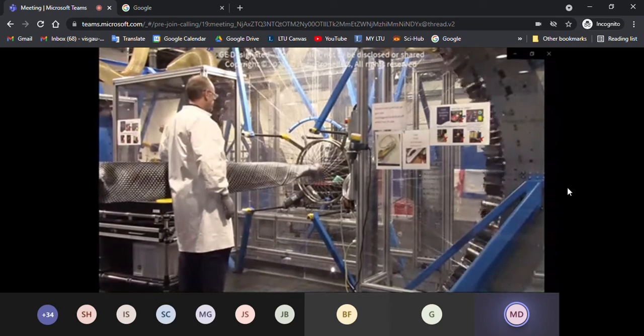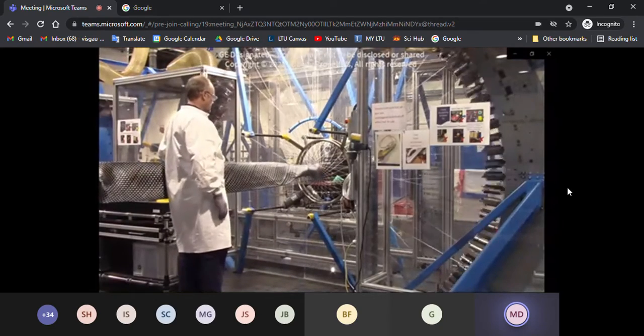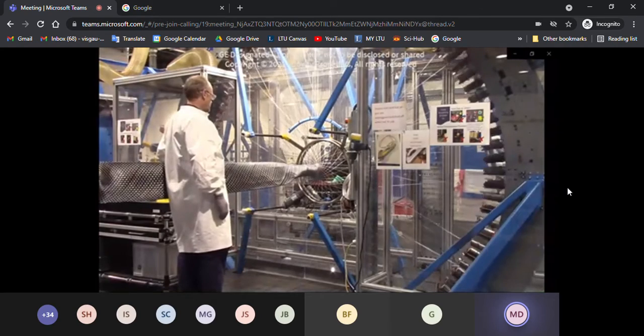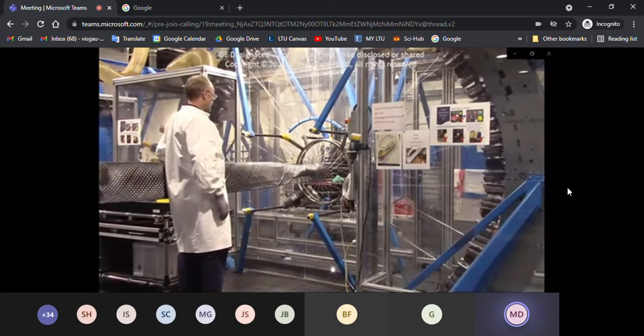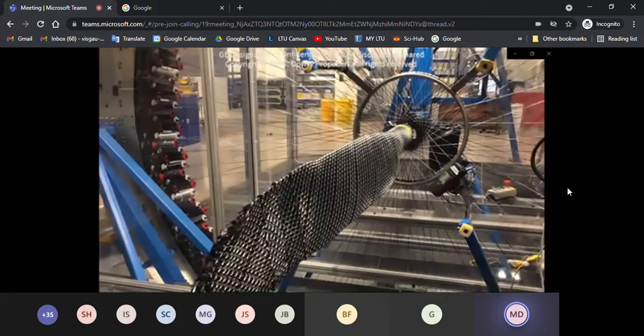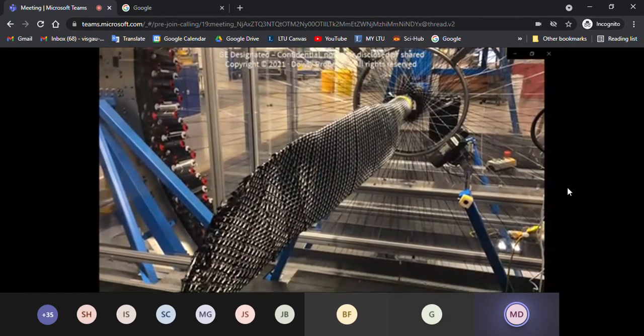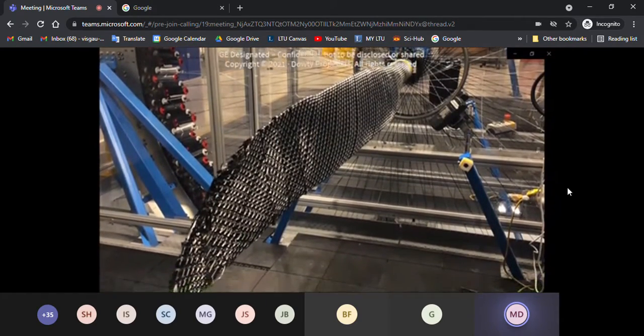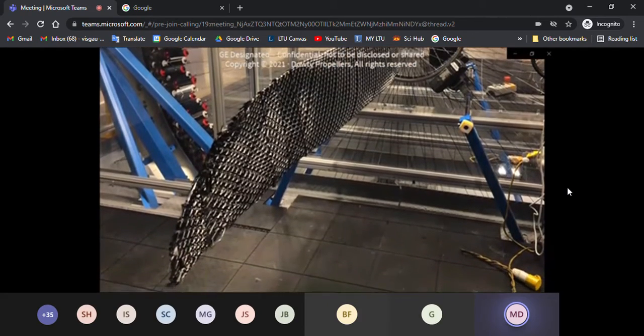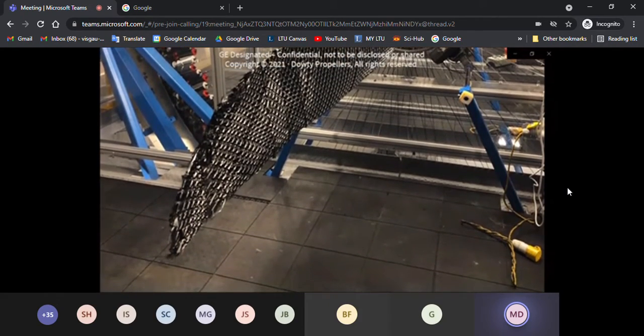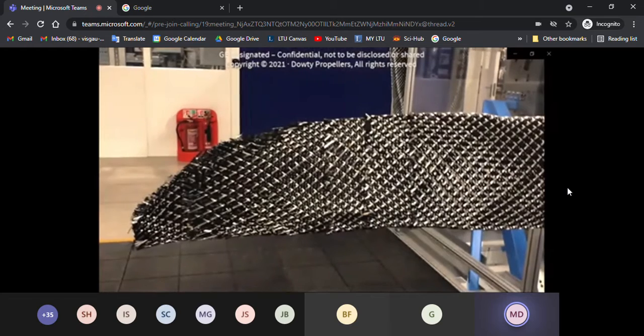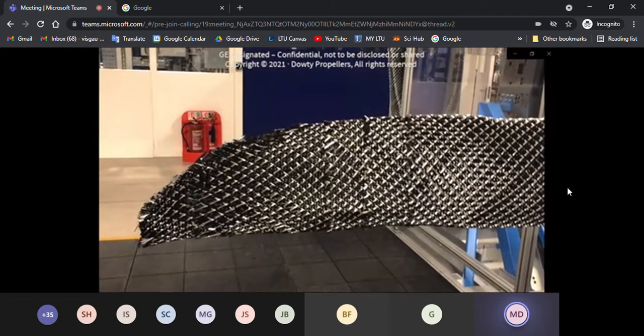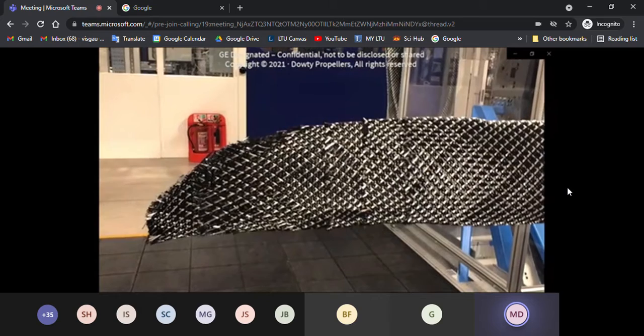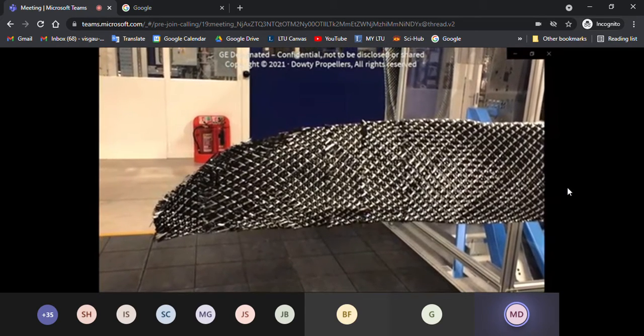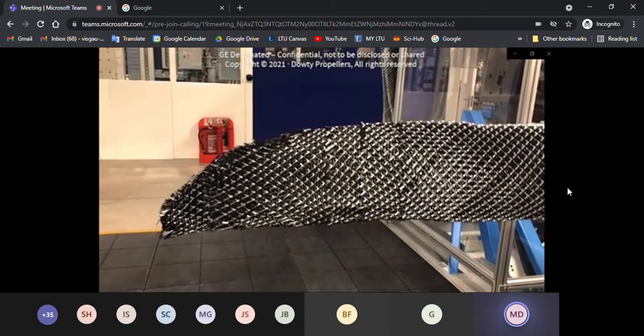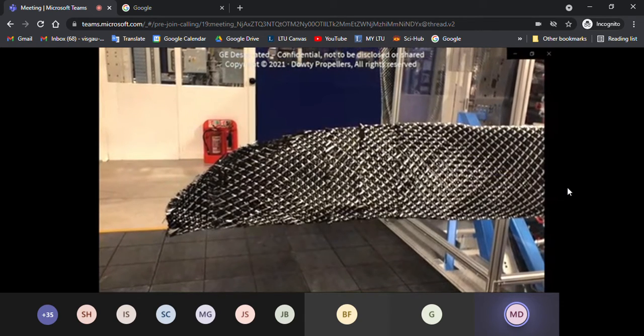So this is not as polished as a production process, but all of our production braid at the moment is military, so this is all I can show you at the moment. And you can see here a fully finished braid preform with ply drops trimmed into the preform. The edge of the braid is a little bit ragged here because it is a development product. But you can see we now have our blade preform fully encapsulated with braid material.